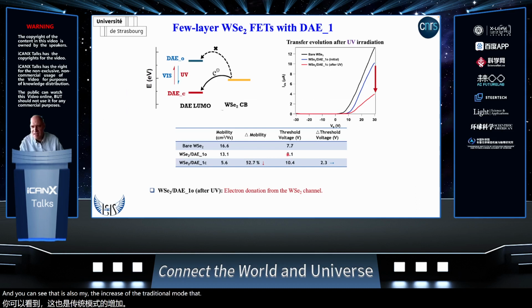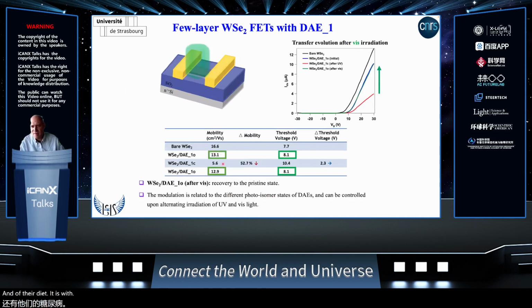Now, if we irradiate with visible light, we are actually able to go back to the initial state of the diarylethene, the open state, and we can see that we go back to the initial mobility of about 13, and also the same threshold voltage. Therefore, we have full reversibility in our photomodulation.